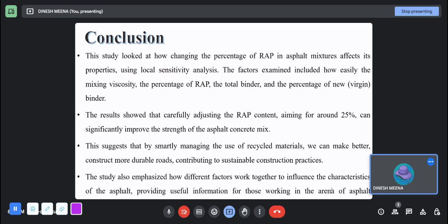Conclusion: the study looked at how changing the percentage of RAP in asphalt mixture affects its properties. Using local sensitivity analysis, the factors examined included mixing viscosity, the percentage of recycled asphalt pavement, the total binder, and the percentage of new or virgin binder. The results showed that carefully adjusting the RAP content, aiming for around 25%, can significantly improve the strength of asphalt concrete mix. This suggests that by smartly managing the use of recycled material, we can construct more durable roads,